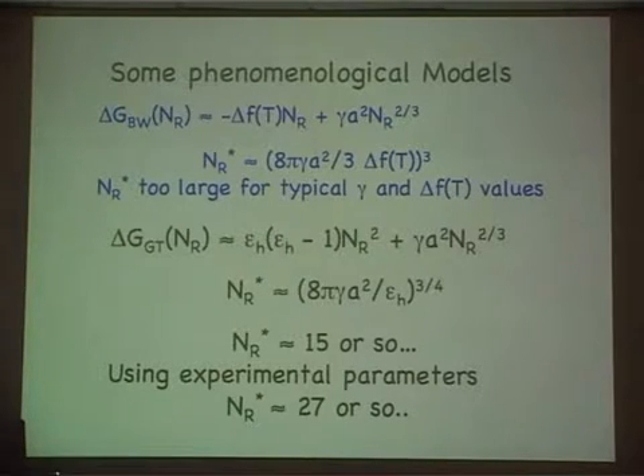Remember, I don't know how to write down very easily what my driving and opposing forces are. One picture of this was to write down the free energy cost of creating NR residues that are ordered as something that goes linearly with NR. I'll tell you the rationale for that. And then the surface area term, which undoubtedly is not correct, which just follows from the homogeneous nucleation theory. The reason this delta F, which is analogous to the chemical potential that you're familiar with, is the amount of free energy that will be gained by a residue that forms a native contact with respect to the unfolded state. Seems pretty reasonable to write this down. So that's the first term, and this opposes that.